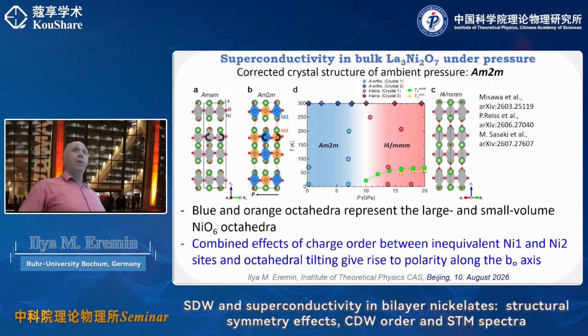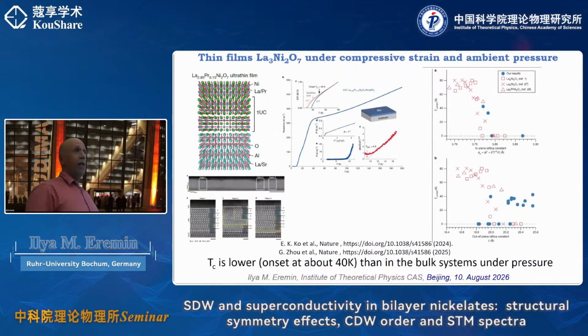Okay, however, to study the system under pressure is difficult, especially if you want to do some thermodynamics. So we gain a lot of information from studying films. It quickly turns out that you can grow films tetragonal from the very beginning, provided that you grow them under some compressive strain. So you have to choose a particular substrate which provides a compressive strain, and then it becomes superconducting. That has been shown by Harold Hwang and also by one Chinese group, who grew on lanthanum strontium aluminum oxide, which provides something like 2.1% compressive strain, where they reach superconductivity.